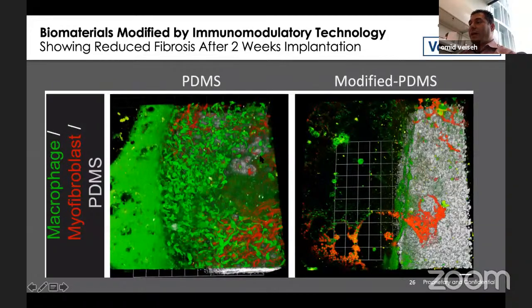The material is in white, and this is the immune response that's mounted to the unmodified material. So you can see a lot of macrophages and myofibroblasts on the surface of the material, but also adjacent to the implant, many millimeters away, we see a lot of inflammation, a lot of macrophages that are present there. And this would be a cause of significant pain and discomfort to a patient that would have this type of an implant. By contrast, when you have the modified PDMS, you actually see very few immune cells, no signs of inflammation, and the material is better tolerated by the host.